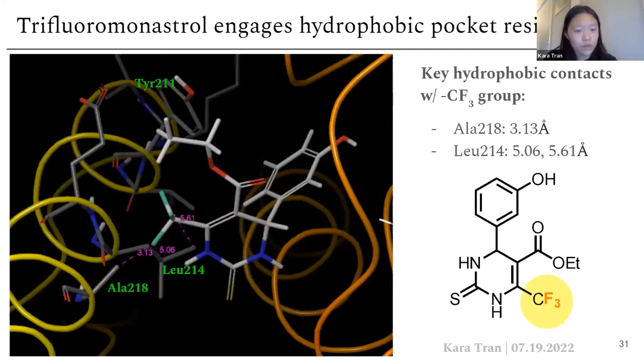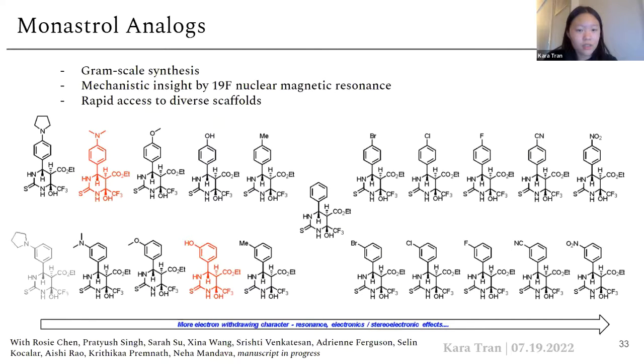Here, trifluoromonastrol is docked, and you can see here that it engages in hydrophobic pocket residues. And here is listed basically the analogs that we made. Through gram-scale synthesis and mechanistic insights through 19F nuclear magnetic resonance, or NMR, we were able to make these compounds synthetically in our own lab. This provides us with pretty rapid access to a diverse amount of scaffolds.